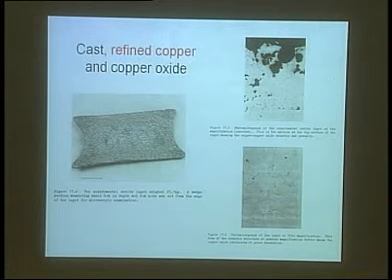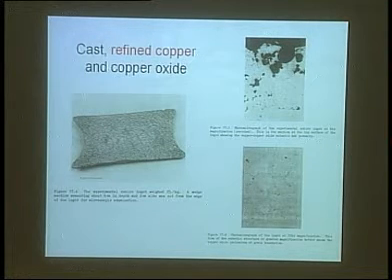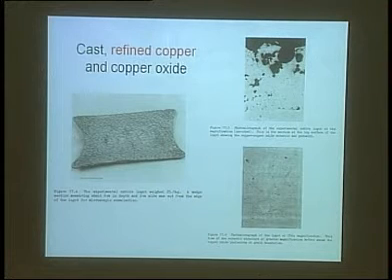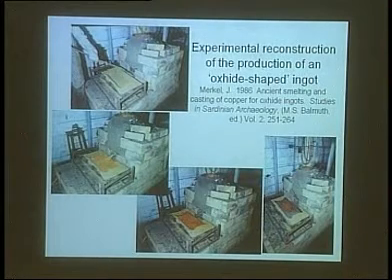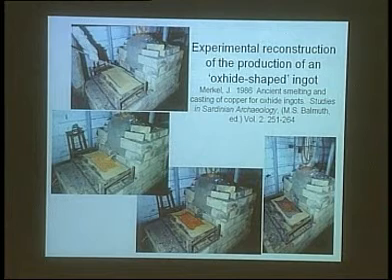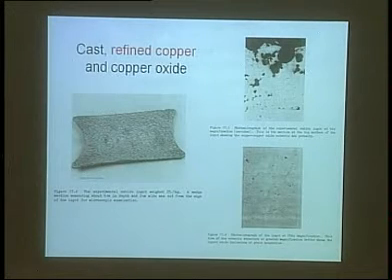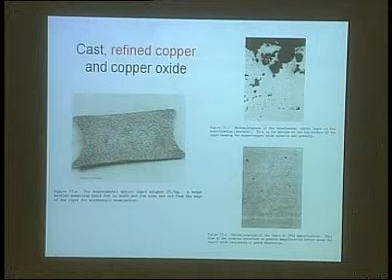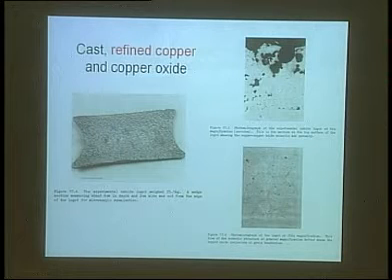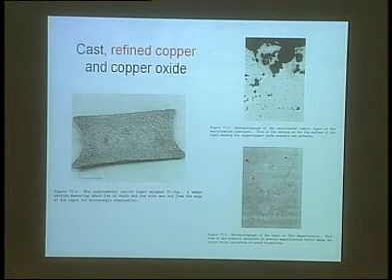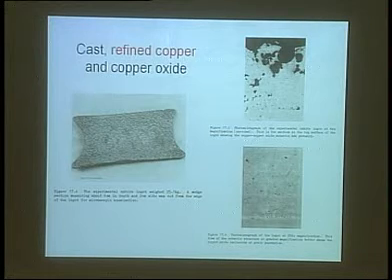And looking at the metallography, some of the background information about this type of ingot, we found that because of the way the copper was melted, it picked up a lot of oxygen, and you can see this in the structure here, but the iron concentration was also decreased. Okay? So again, looking at those processing parameters, that affected the compositions.